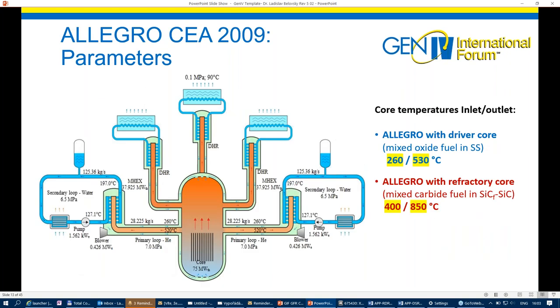Here are parameters of the Allegro preconceptual design by CEA from 2009, very similar to the ETDR, the option with the driver core inlet temperature 260 and average core outlet temperature of the helium coolant 530. In case of the full refractory core, temperatures around 800-850 degrees C are planned, with 400 degrees C inlet temperature to the core.